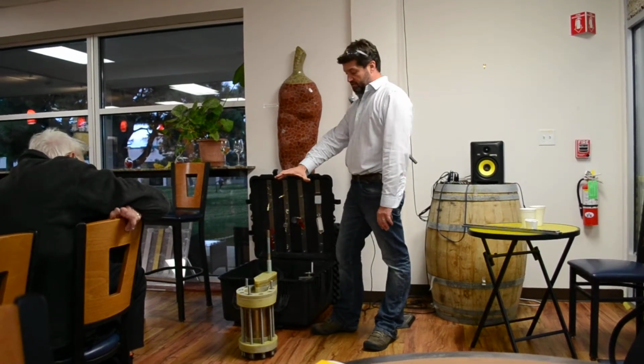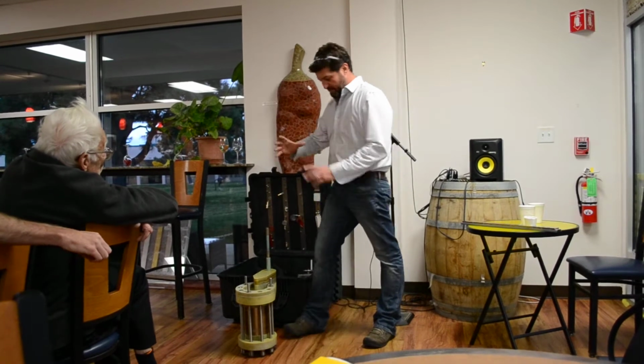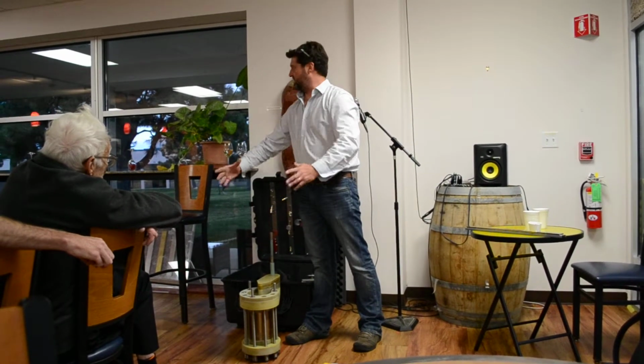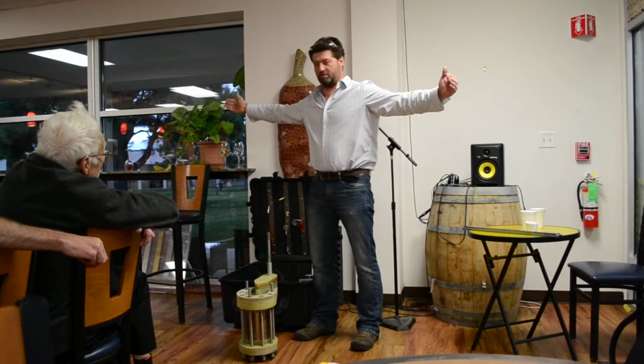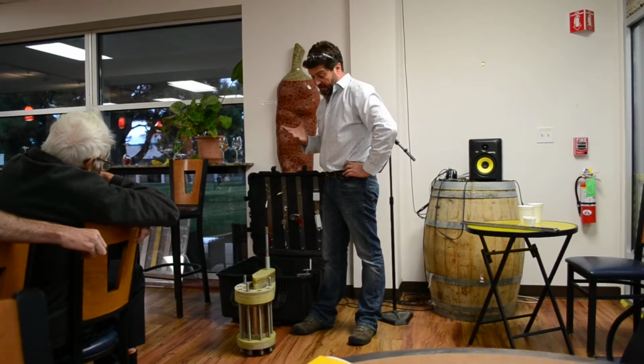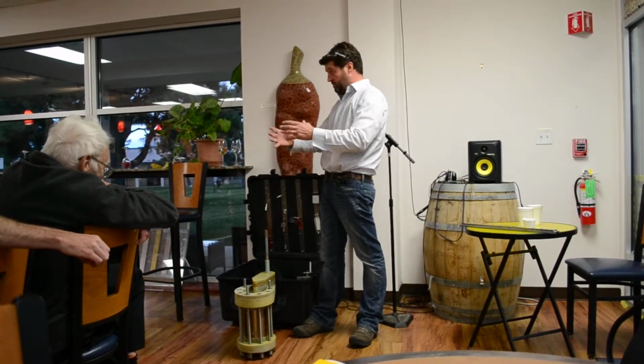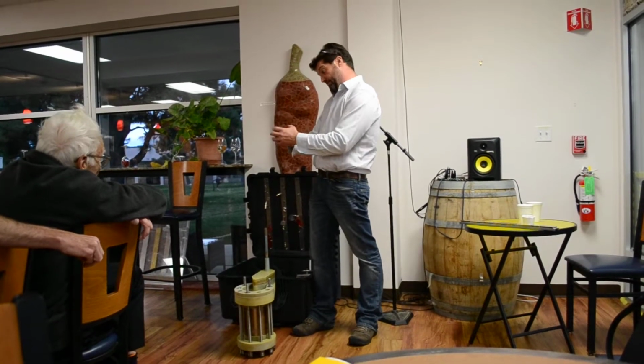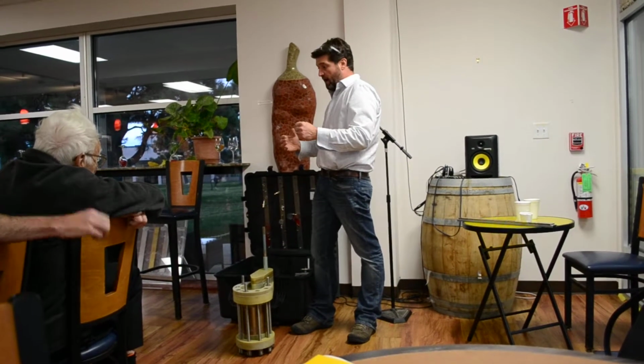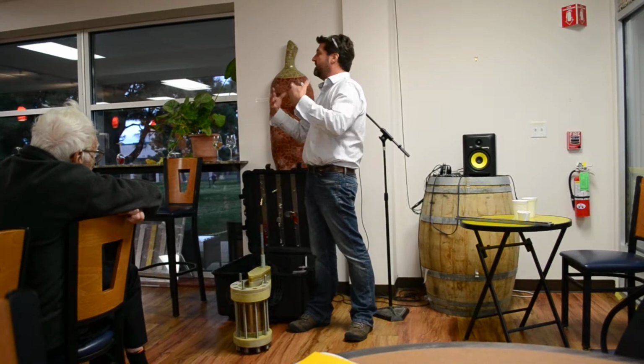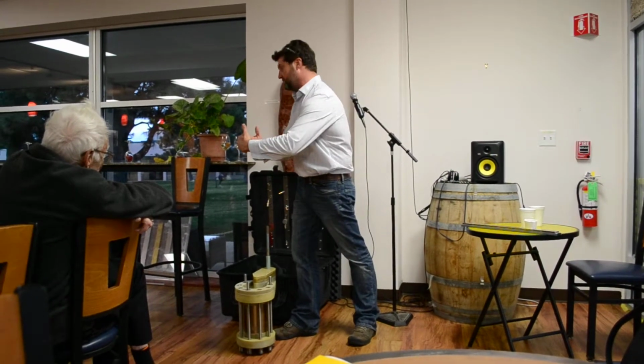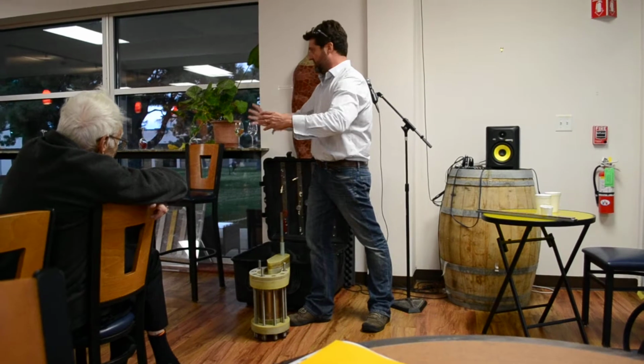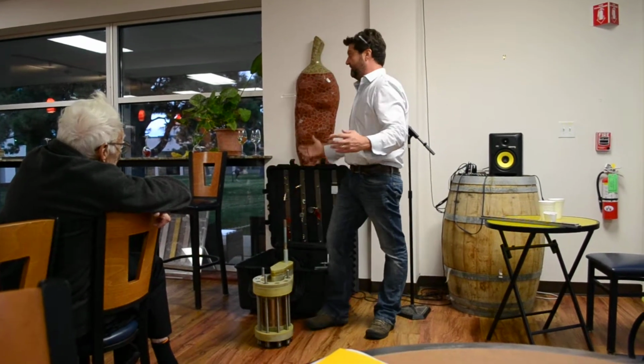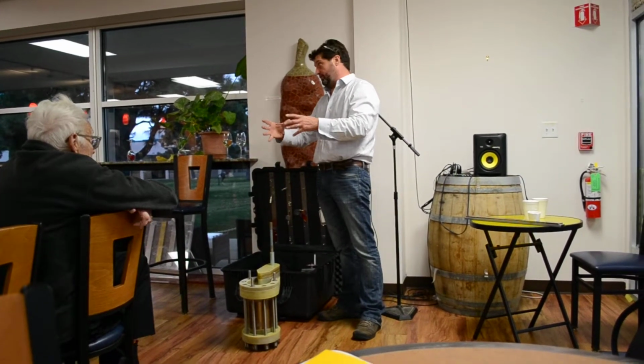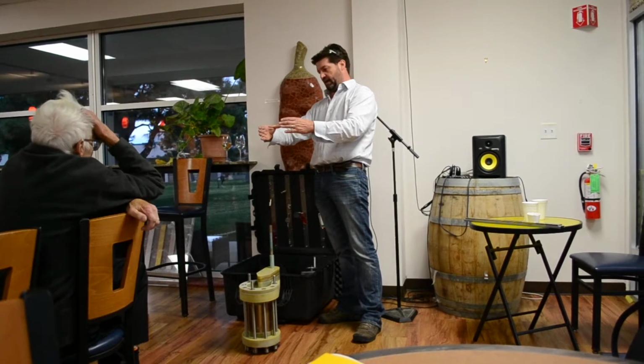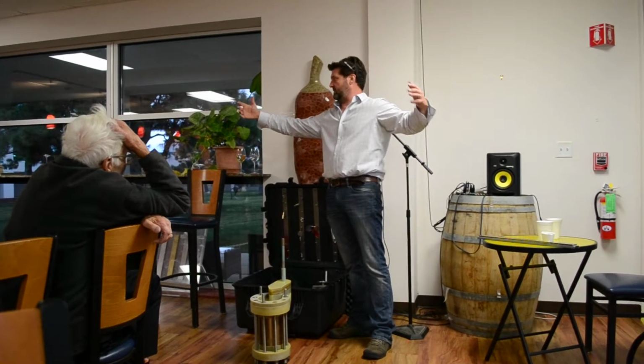A magnet that goes to 100 Tesla is basically this inside another magnet, inside another magnet. It's like Russian dolls up to about this size. Now the reason for that is basically you're distributing these huge forces and these loads that the magnet wants to rip itself apart. But as you do this, you get into this sort of runaway solution. I put in my reinforcing material, and then the next coil around the outside is even bigger, so then I need even more energy to power it, more power, importantly, how much energy per unit time you can get into the magnet, and it gets bigger, and it gets bigger, and it gets bigger.